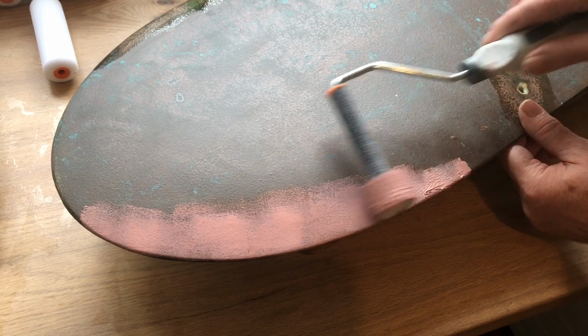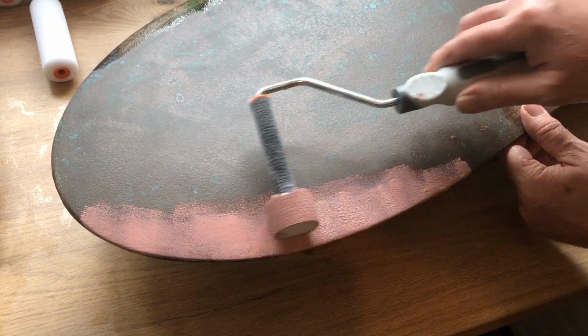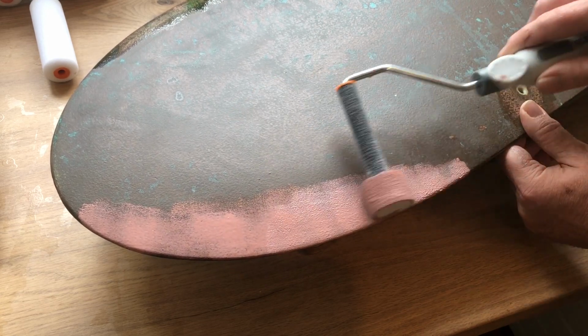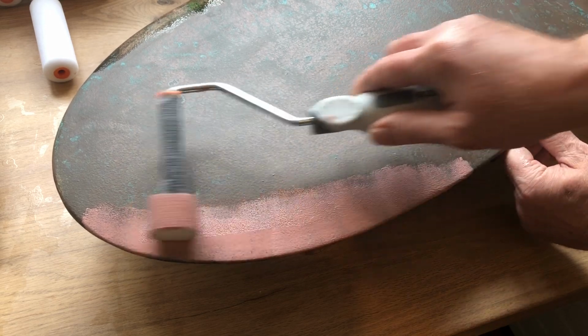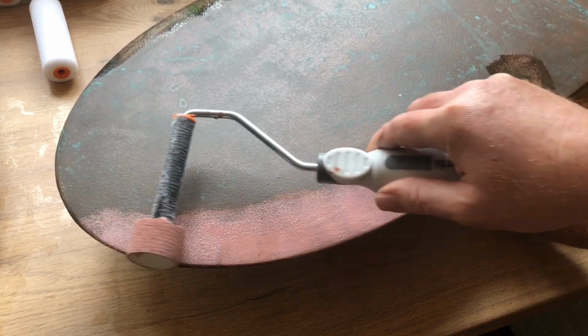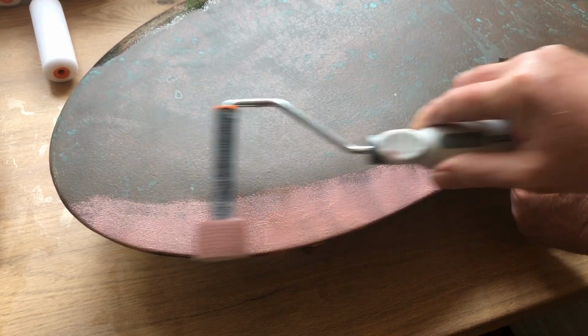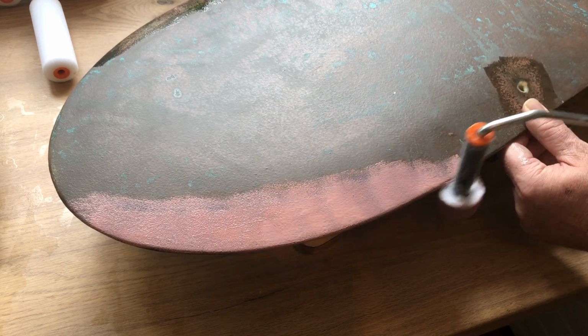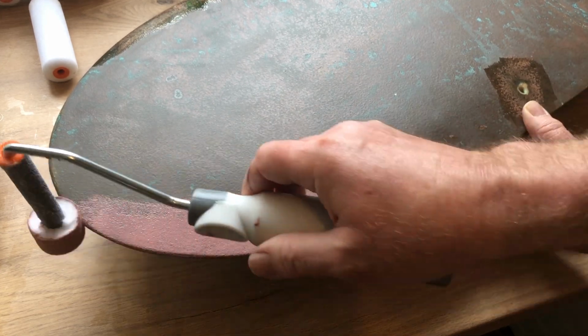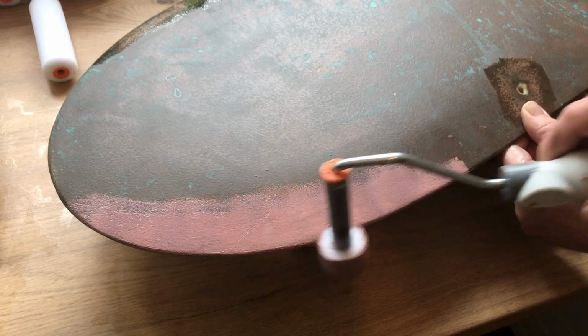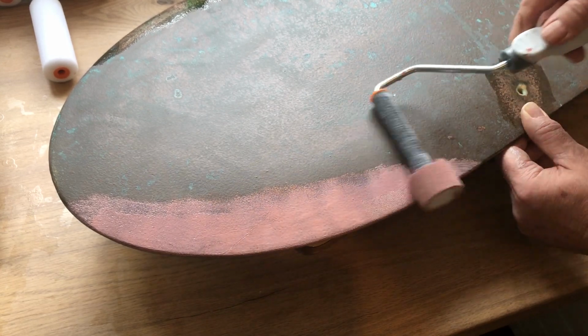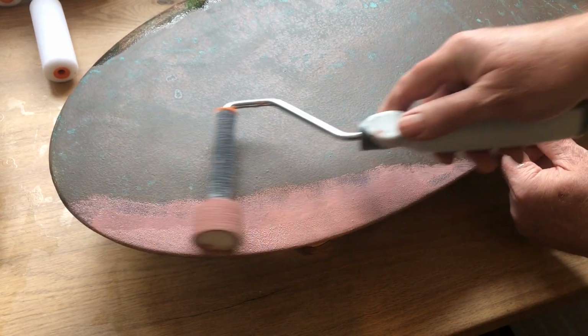The pot life of Coppercoat is approximately 40 minutes at 10 degrees centigrade, 30 minutes at 20 degrees and 20 minutes at 30 degrees. To avoid waste, I mixed just the amount I needed prior to applying each coat. I kept checking the tackiness of the drying coat to determine the right time to weigh and mix the next batch.